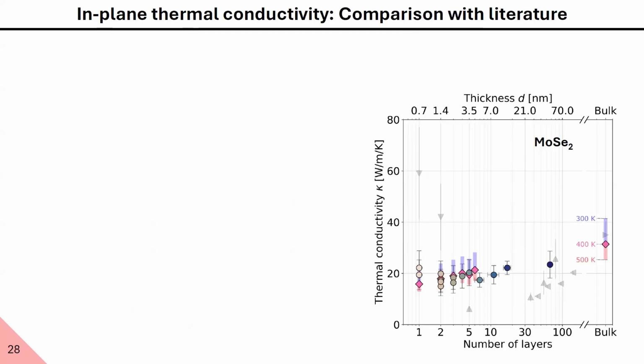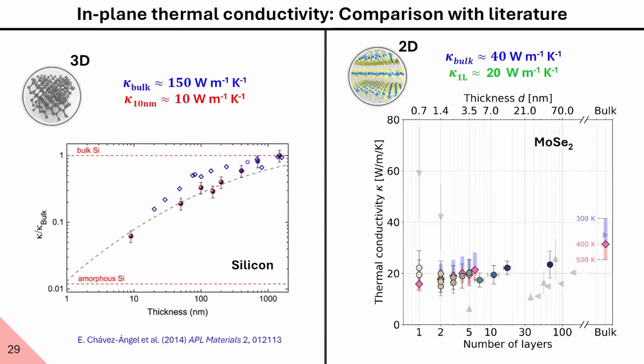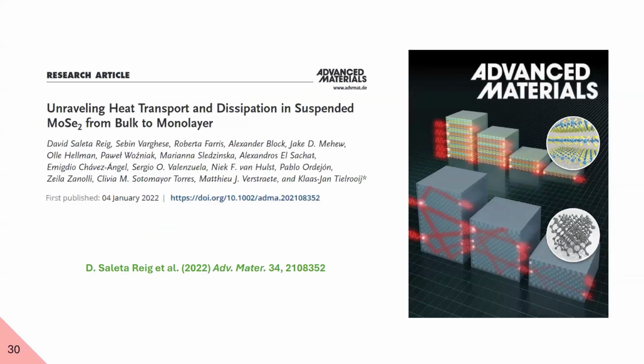So how does this compare with literature? Well, we really filled the gap. So back to the case of silicon, this is as if our 2D materials, that importantly we can thin down to sub-nanometer thickness, maintain their thermal properties down to the monolayer. We summarized our results in the Journal of Advanced Materials in 2022, this very nice paper where we also discuss the effects of the environment and potential experimental artifacts that can occur in this type of measurements.